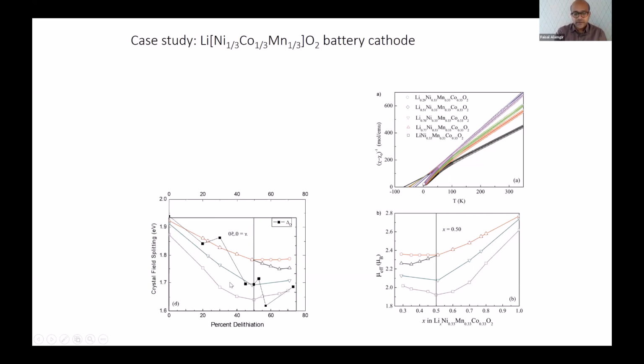And then, not to be facetious now, to come back to the science, if you look at the trend of the de-lithiation and crystal field splitting, the original plot, together with the magnetic moment, you see that there's a trend that is similar. So this downward trend here of the magnetic moment as we delithiate makes sense from the point of view of the electronic structure, in that you are removing unpaired electrons as you're oxidizing the cations. And so there's an average downward trend.